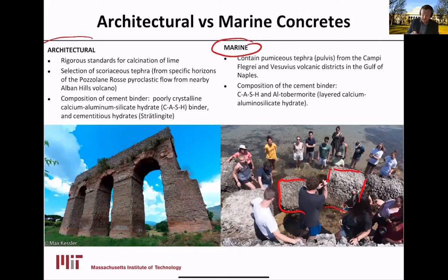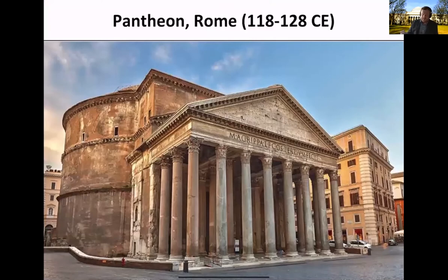But in both architecture and marine mortars, they would use the lime and a selection of these volcanic pozzolans that would differ slightly in terms of final products. In the case of architecture mortars, you would have strätlingite, and in the case of marine mortars, because they are constantly in marine water, some other reactivity would happen, and generally aluminum tobermorite is the material corresponding to it.